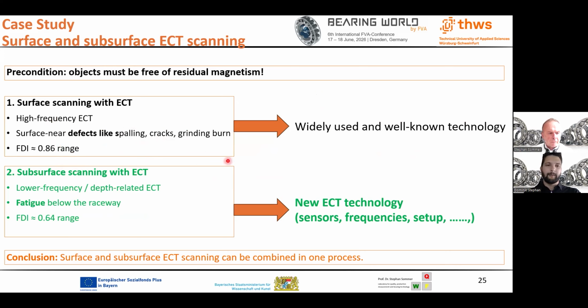The second step is subsurface scanning with lower frequencies and a depth-related sensor setup. This new ECT approach aims to detect fatigue below the raceway, where no visible surface damage may be present. A precondition is that the object must be free of residual magnetism, because residual magnetism can influence the ECT signal. The key message is that surface and subsurface ECT scanning can be combined in one process, for example, in bearing refurbishment.